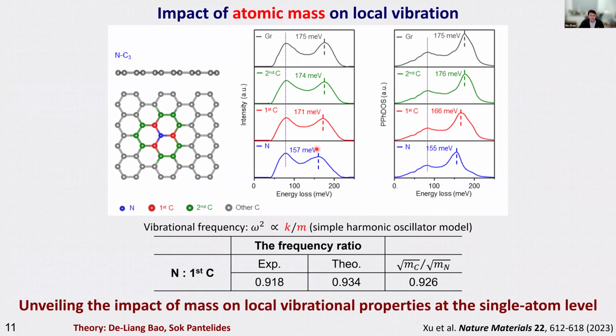We can see in this case, the optical phonon mode will shift. And if you just measure the frequency, it matches with what you can predict with a simple harmonic oscillator model, square root of the mass ratio. So that means that we actually see both, we can decouple both.